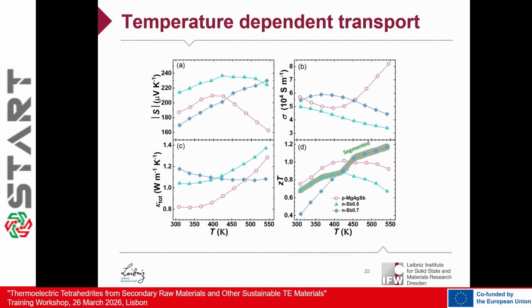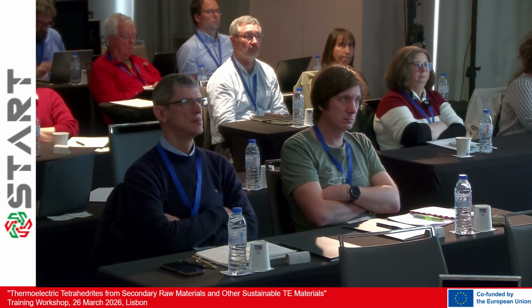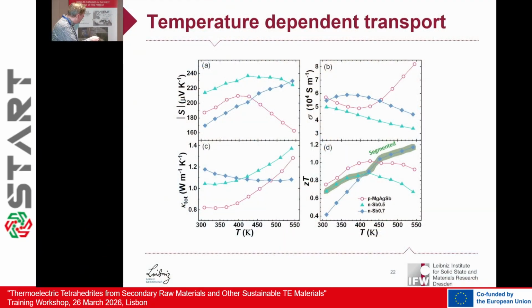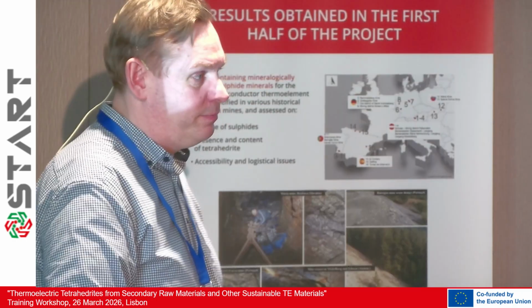When we do this combination, this gives you an overview of the thermoelectric properties. The Seebeck coefficient is rather high over the whole regime, I would say. Electrical conductivity is also rather good. But the important factor is the ZT you can see here. When we combine the segmentation for the N-type materials, we keep it on a very high level over the whole temperature regime. And in comparison with the P-type material, also over the whole temperature regime, we are close to a ZT of 1.